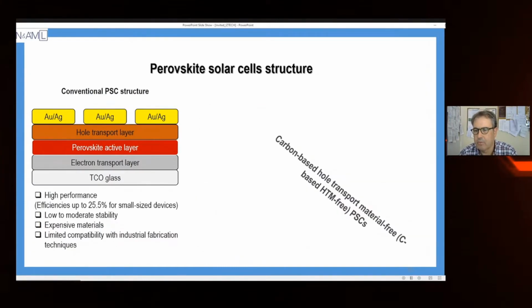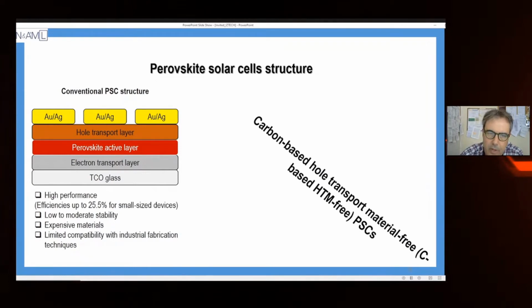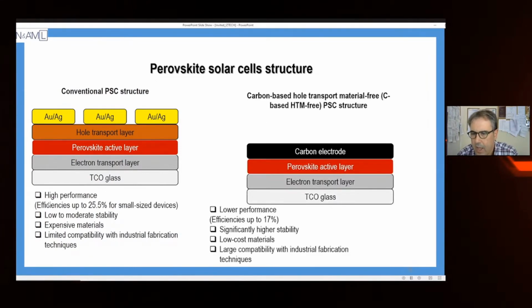That's why, as I said, we transferred the technology from this basic structure to that with carbon. This is the simplest structure that we can follow, with an electron transport layer, a perovskite and the carbon electrode. As I said also before, the efficiency now for the current technology is 17%. We have very good stability. The cost of the materials cannot be compared with the previous structure here. And of course, the best thing here is that we have large compatibility with several industrial fabrication techniques.